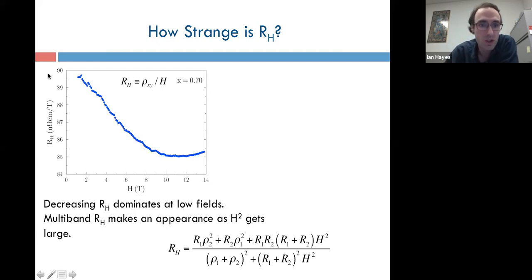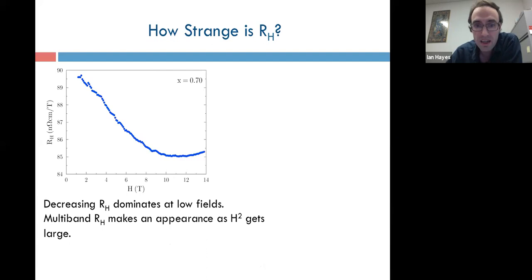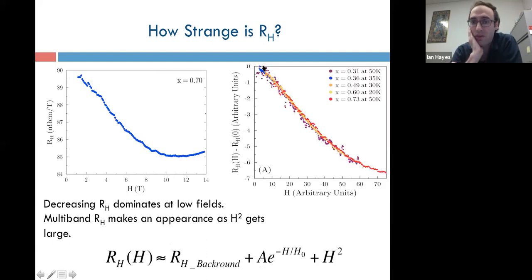I just want to show you more generically what RH looks like. So in the rest of the talk, I'll just plot RH, which I'm defining here to be rho xy over the field, because that's what makes it easiest to see the field dependence. And so generically, what you see throughout the phase diagram is some region of decreasing RH, which flattens out, the field dependence decays, and eventually you get an upturn, an increase in RH at high enough field. Since that's what we expect from multiband physics, that's naively what we'll attribute it to. And in fact, you'll see eventually when you get to the far overdoped side of the phase diagram, pure H squared is in fact what you see. Other than that H squared, the curve is sort of generic.